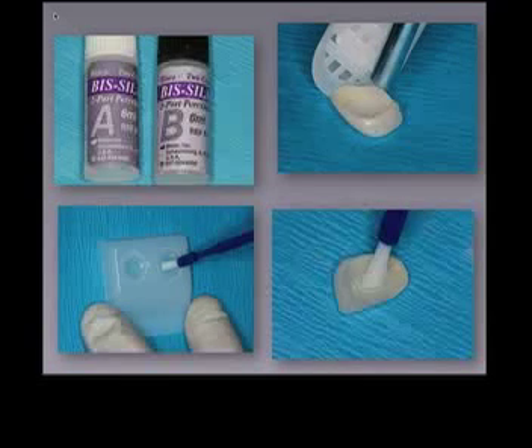Air dry, again, warm air is best. The hydroxyl group of hydrolyzed silane reacts with the hydroxyl group of the ceramic to form water. It's a condensation reaction, and air drying speeds this reaction up far more than it would occur on its own. So this is very important.